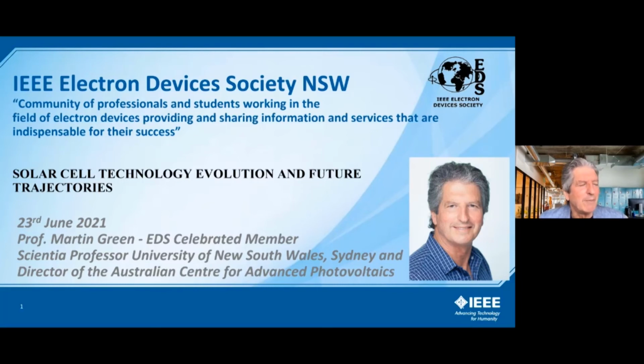But now, as I mentioned, the industry is going to gallium for doping, and part of that reason is to address light-induced degradation. There have been techniques developed, some at our university, for mitigating light-induced degradation in boron-doped wafers, but the industry seems to not be taking any chances and is going to gallium-doped wafers to avoid those issues. So with a module from a recognised supplier these days, there shouldn't be any issue with light-induced degradation, although it has been an issue that has occupied a lot of attention over the last decade. So thanks for the question.